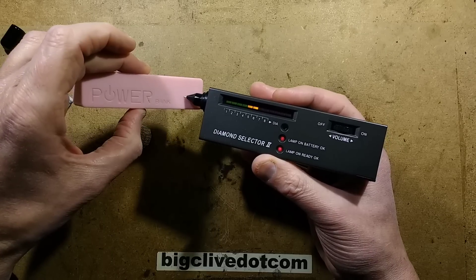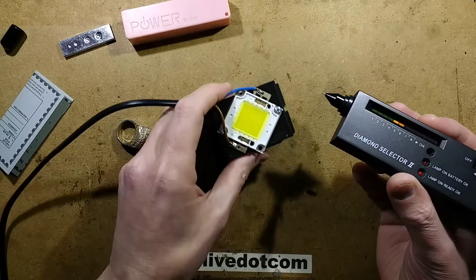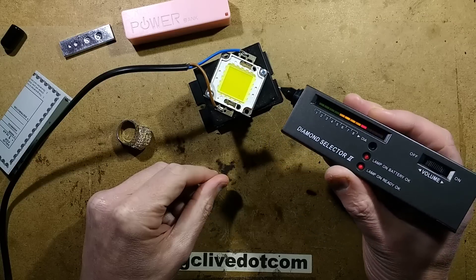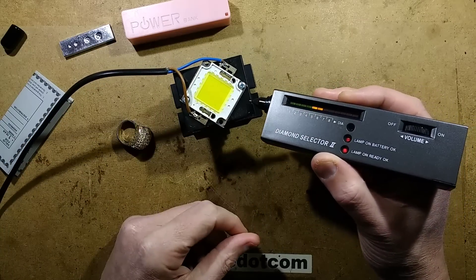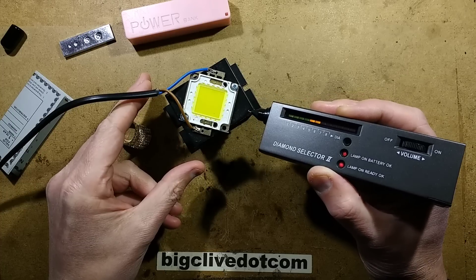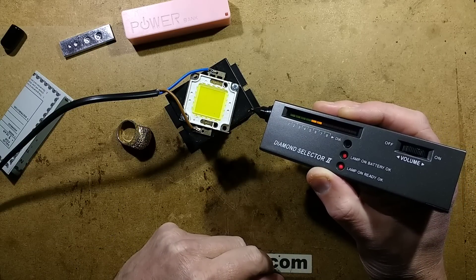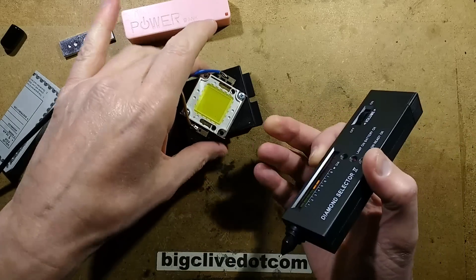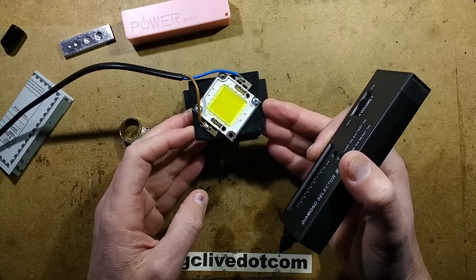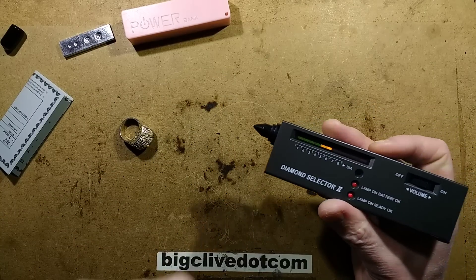One technique is adjusting the bar graph: it has three green LEDs, three yellow LEDs, then three red LEDs — the red LEDs indicate diamond. You'd calibrate it on a similar diamond in a similar setting, adjusting it to just peak to that level according to ambient room temperature and gem size. If I touch a non-thermally conductive surface, nothing happens. Touching a metal heat sink, it shoots right up — sucking heat away from the tip very quickly. Interestingly, touching the anodized surface of the aluminium doesn't take heat away, but the bare metal does, suggesting the anodization reduces thermal conductivity contact.